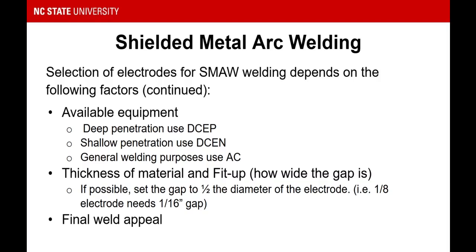The thickness of the material and the fit up, if possible, if you're welding two pieces of material together, like you saw on the paper a few minutes ago under the doc cam, you want to put those pieces of material so that the gap between the two pieces of material is half the diameter of the electrode itself. So if you're using a 1/8 inch electrode, you want about a 1/16 gap between the material. That's important because when you're welding materials together, if you don't either bevel the edges or put angles on the edges or leave a gap, the weld will not penetrate down throughout the material. And so while you'll weld the surface, it won't be a very solid weld.